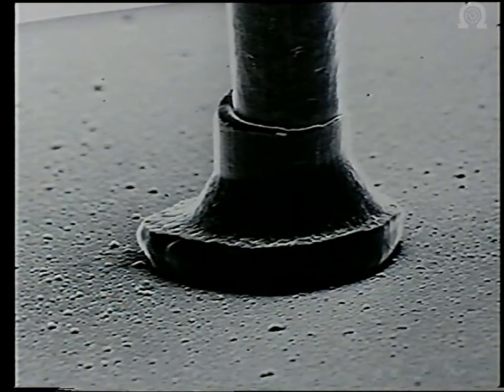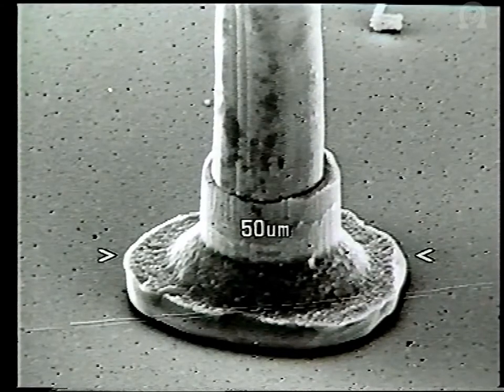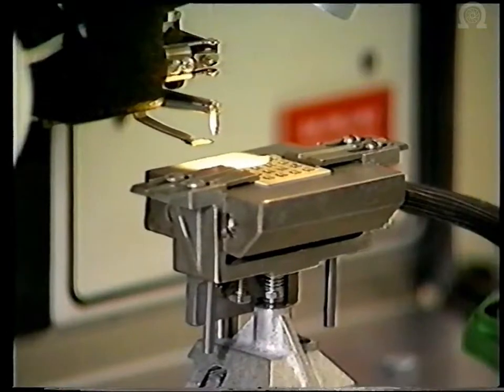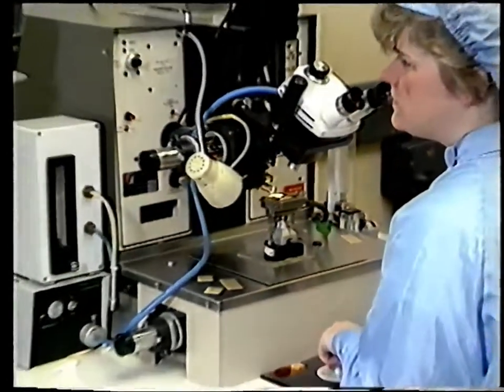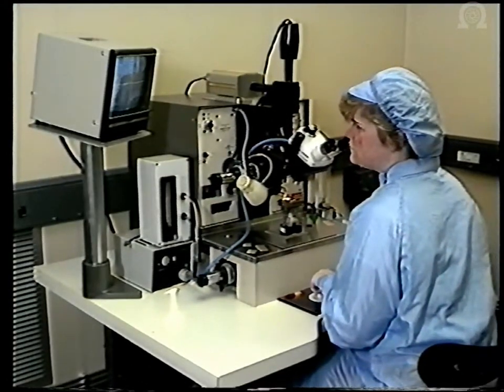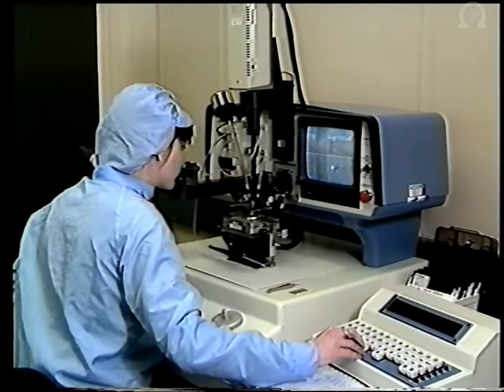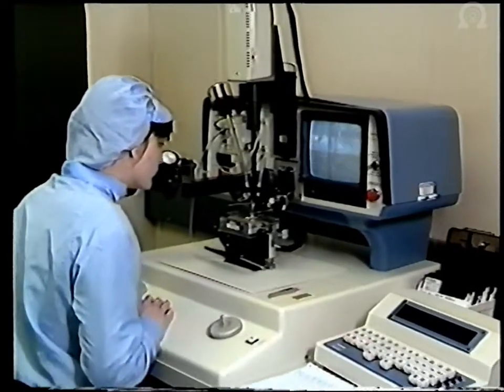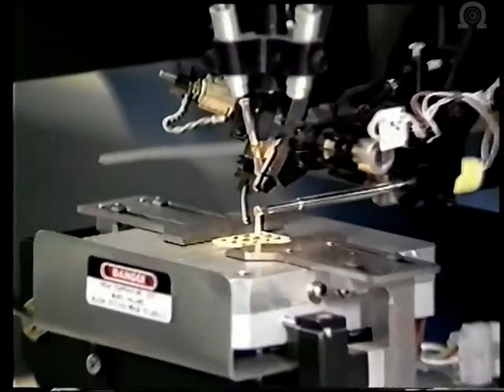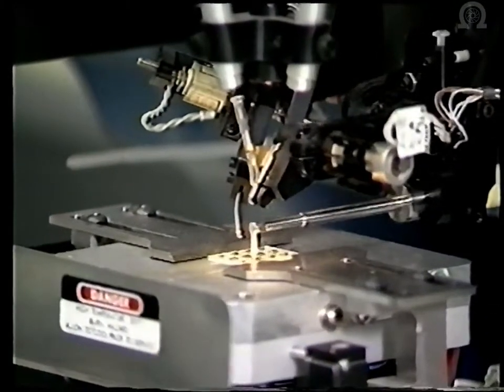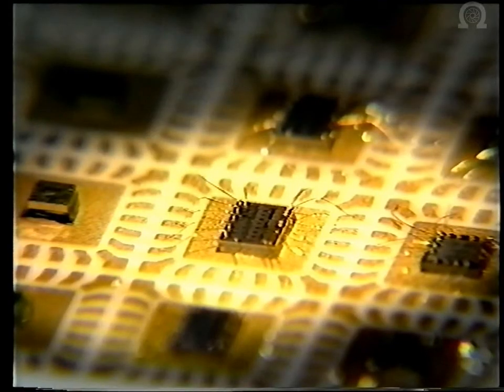Good quality bonds down to 50 microns in diameter have been made using 17 micron diameter gold and copper wire. Aluminium, gold and copper ball bonding techniques are also being investigated on automatic wire bonding machines, shown here. These are capable of bonding speeds of up to 3 loops per second. Bond quality is usually assessed by destructive testing.